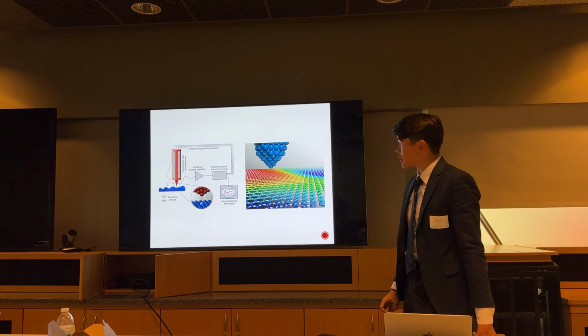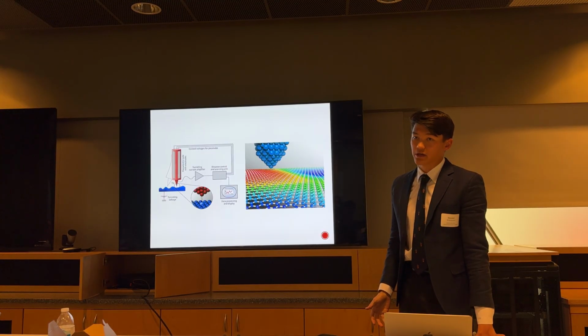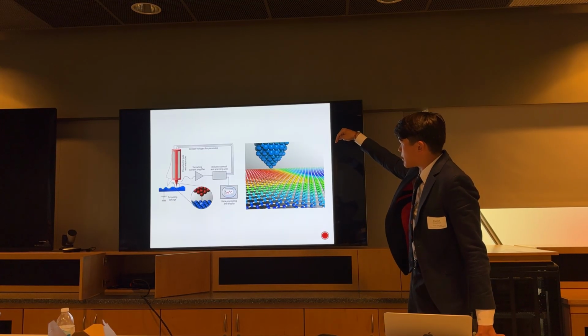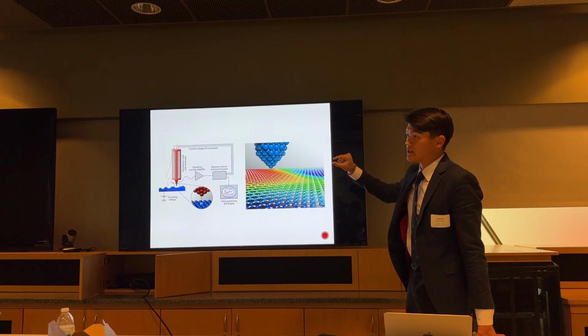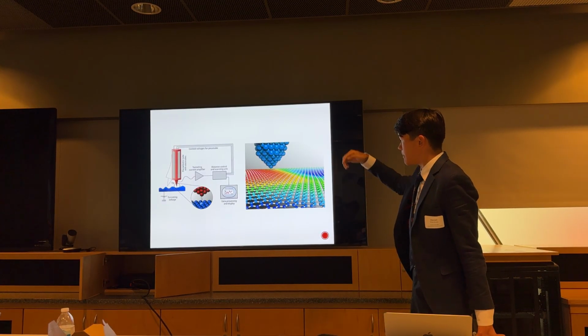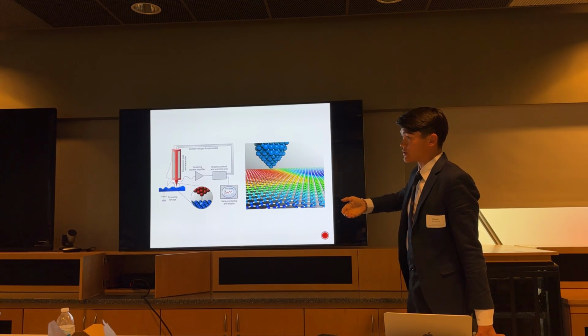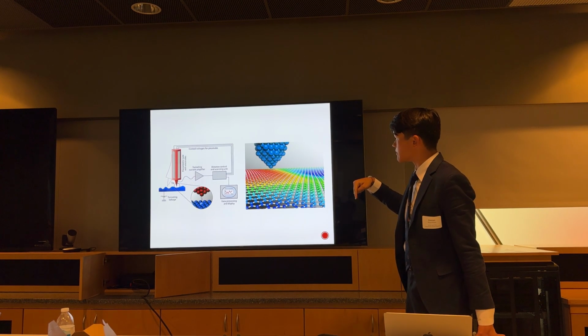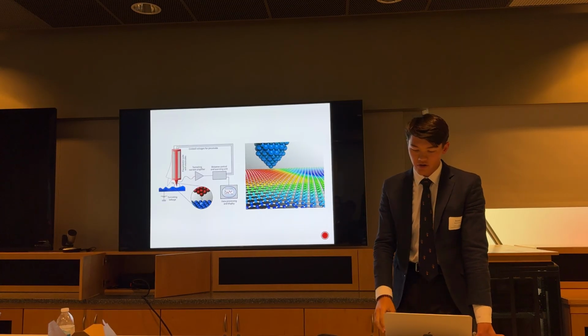Here are two diagrams of scanning tunneling microscopy, which is where a very sharp tip lies about a nanometer above the surface of a sample. And it moves around, and by passing a current through it, whose electrons are quantum tunneling, you can move the tip around and find the geometry of the sample. So this is a principle that's very much tested.